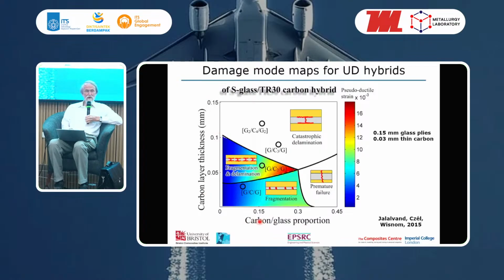So the proportion of glass and carbon affects whether it fails catastrophically due to fibre failure. If we have too much carbon, we get this premature failure of the whole laminate when the carbon breaks. But if we have less carbon, then we don't get that failure mode. On the other hand, if the plies are too thick, then when the carbon fails, we'll get delamination. But if the plies are thin and there's less energy, then we can get fragmentation or fragmentation with a little local delamination, and then we're in this gradual failure domain, and the colours here are indicating the expected pseudoductility.